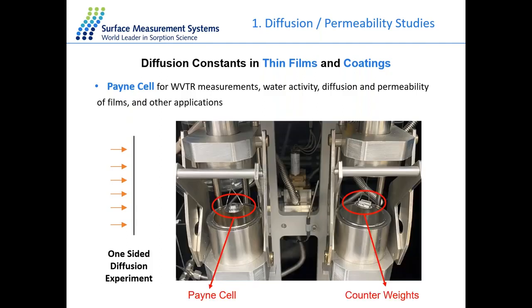And this simple Payne cell is just an additional accessory to be put inside the sample pan like this one. Because the weight of this Payne cell is beyond the dynamic range of the balance, in that case, you need to put some counterweights on the reference side to compensate for the weight of the Payne cell on the sample side. So we need to put both the counterweight and the Payne cell in the system.